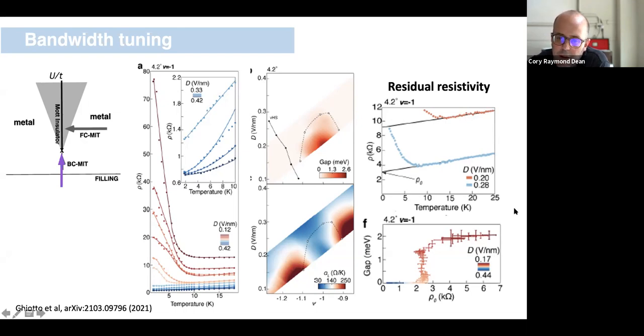resistivity value there. And if we plot that residual resistivity as a function of displacement field, we see that it's roughly a constant value, and then it abruptly transitions to a zero value.